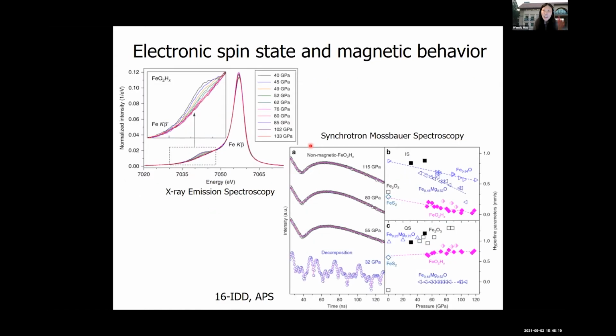Okay, so we can also look at the electronic spin and magnetic behavior of iron-bearing compounds. The electronic spin state of iron, the iron 3d electrons, as Renata also showed us earlier today, can be probed by studying the iron K beta fluorescence via X-ray emission spectroscopy. What we actually saw is that the intensity of this K beta prime peak, this little shoulder here, decreases between 45 and 60 GPa, and then it disappears around 60 to 65 GPa. And this indicates the total spin momentum of the iron in this FeO2 phase is approaching 0, and that this phase undergoes a spin pairing transition around 65 GPa from high spin to low spin.